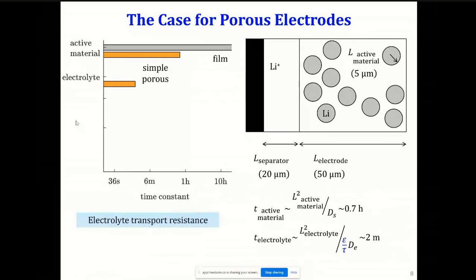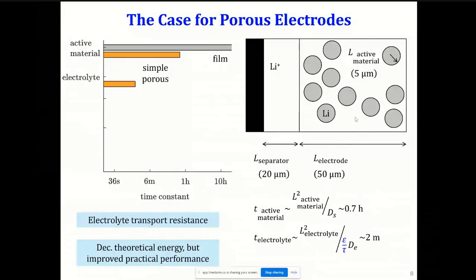Another conscious choice we are making with this is, if you compare with the previous version, where the entire electrode volume was filled with the particle that can store lithium, that means it can store more lithium as compared to this configuration, right? So if we just compare the theoretical capacity energy of the previous configuration, which is the film electrode, and a porous electrode, you're bound to get a lower theoretical energy. The advantage that you get out of this is that you are improving the transport. Now you will get a much better practical performance. You will be able to charge the cells in an hour, right? Unlike the 10-hour limit that we had previously.